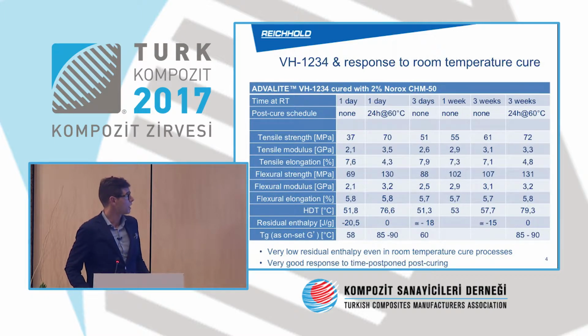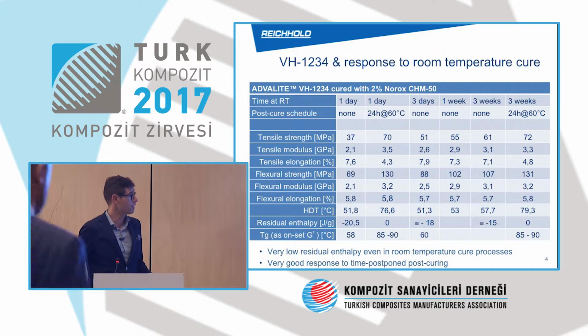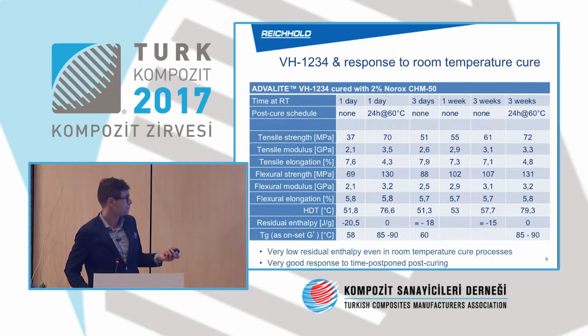And as you can see, after just one day without post-curing, you can get good HDT, good residual enthalpy, and good TG. And after 3 weeks, with only 24 hours at 60 degrees, you achieve 100% of resin properties. So it means that you have a good elongation, similar to vinyl ester resin. Residual enthalpy is close to 0, and HDT is close to 80 degrees. So performance of the resin is guaranteed also without post-curing and in a really short time.